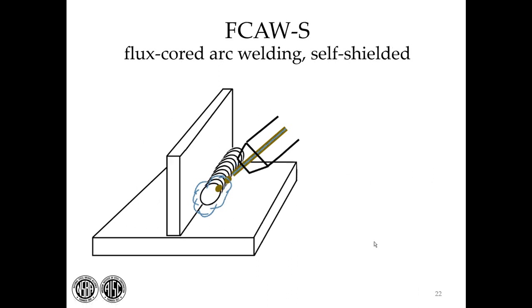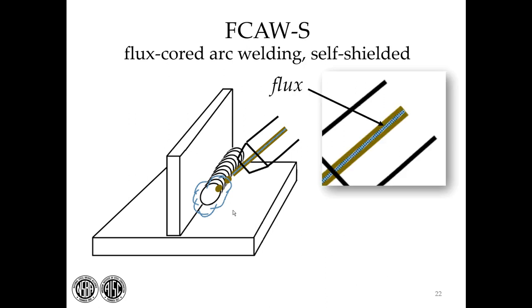You see the gas for shielding. You also get self-shielded flux-cored, and in this case there is no gas, but the flux itself is burnt and provides a shielding. We don't prefer that in the shop. We readily have gas, but sometimes it's useful if you're in a more remote situation or perhaps out in the field where you don't have gas and you want to just use the flux in the core of the electrode for shielding. That's the flux.